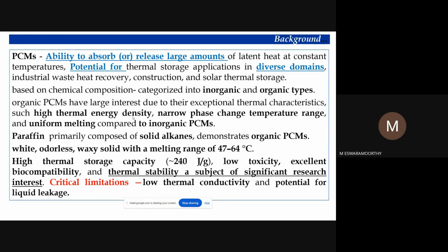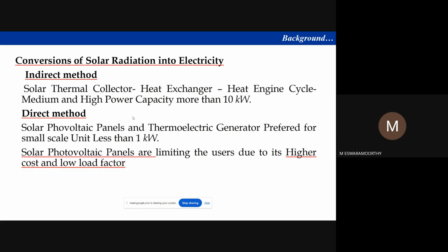Paraffin is composed of solid alkanes, a typical organic PCM. White, it is an odorless, waxy solid with a melting range of 47 to 64 degrees centigrade. It has a high thermal storage capacity of 240 joules per gram. Low toxicity, excellent biocompatibility, and thermal stability make it a subject of significant research interest. Its critical limitations are low thermal conductivity and potential for liquid leakage. The liquid leakage can be avoided using composite phase change material.